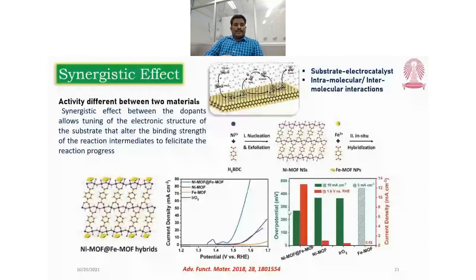The synergetic effect is the activity difference between two different MOFs. When two MOFs are mixed with one compound, that compound tunes the electronic surface structure, which alters the binding strength of the intermediates. This is favorable for the ORR and OER reactions. For example, when nickel and iron MOFs are well mixed, they can perform OER activity and give better performance compared with precious catalysts.